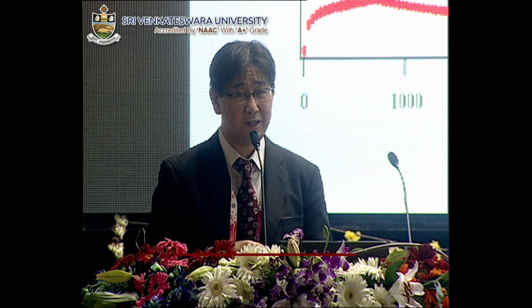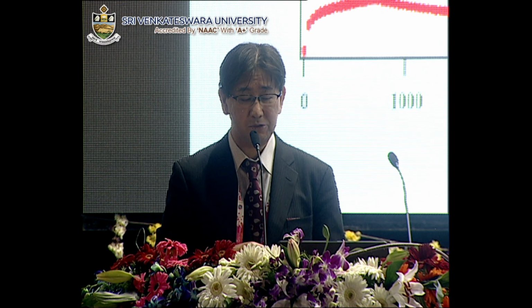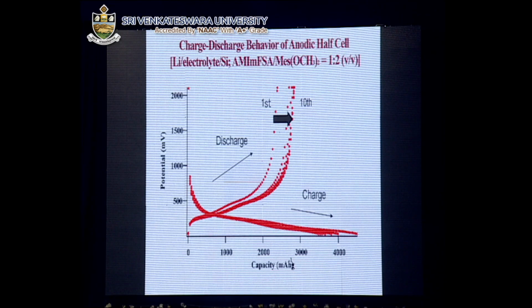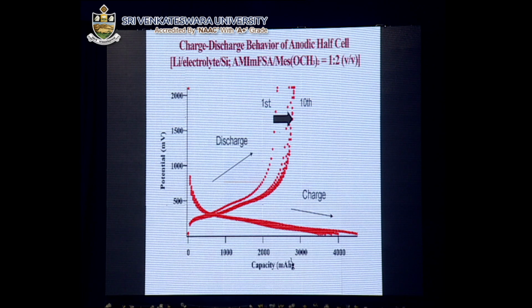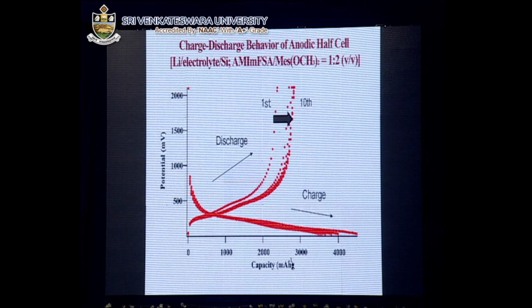So by utilizing this electrolyte, we have fabricated a lithium-ion battery composed of lithium foil, the electrolyte, and silicon anode materials. And as you see, a reversible charge and discharge profile was observed, and the maximum discharge capacity reached approximately close to 3000 milliampere hours per gram. And interestingly, with increasing number of cycles, a gradual increase in the discharge capacity was observed, possibly due to the formation of a fairly conductive surface layer, an SEI layer, on the electrode surface.